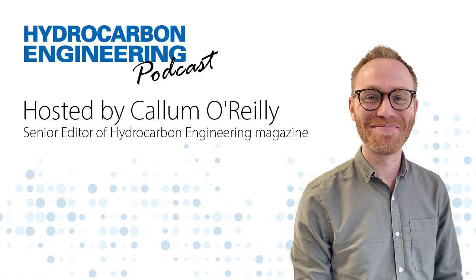CUI occurs at the substrate and insulation interface where moisture makes its way and breaks through the cladding and becomes trapped inside that mineral wool insulation. CUI has an accelerated corrosion rate due to the combination of heat and trapped moisture, creating an environment that's exceptionally well suited to the formation and proliferation of corrosion cells. In addition, the cladding keeps the substrate and corrosion hidden, causing concerns with inspection and catching the corrosion before it becomes a major problem. Now, we have a coating that can actually eliminate the potential for CUI in some temperature ranges, but I'll leave that discussion for another day.